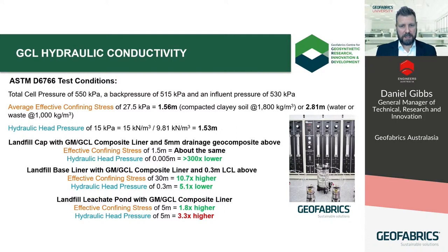As you can see by these examples given here, while the less than 5 or less than 3 by 10 to the negative 11 meters per second has now been embedded into industry specs for over 20 years based on a deionized water test, it's important to consider that actual hydraulic flux will change depending on the application and particular site conditions, including changes to overburden or confining stress, hydraulic head pressures, and the composition and concentration of the permeating